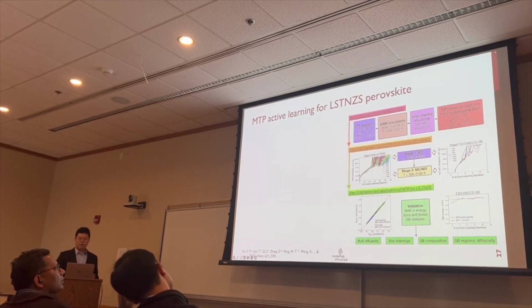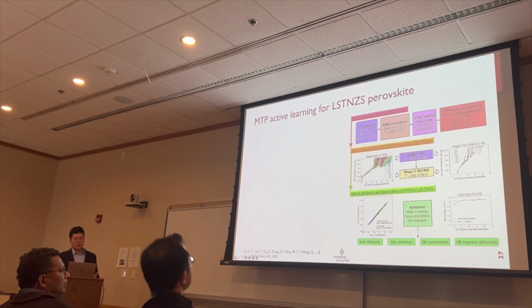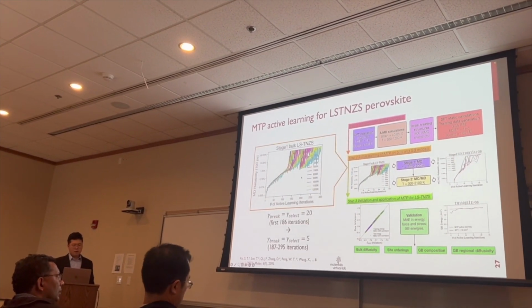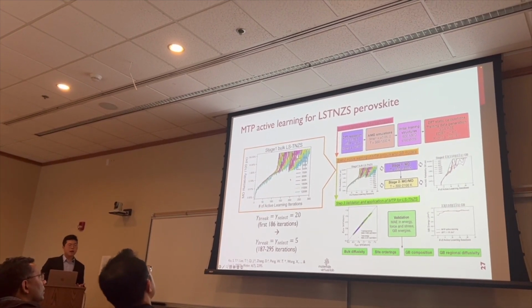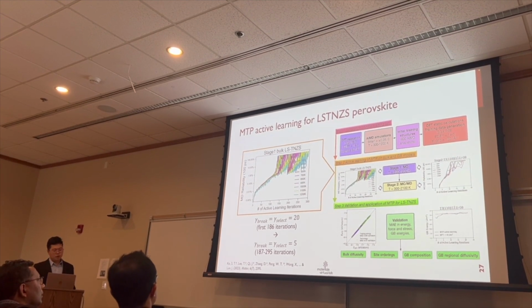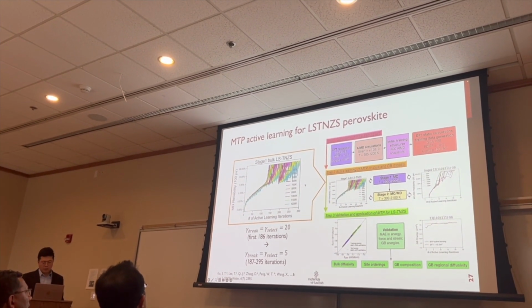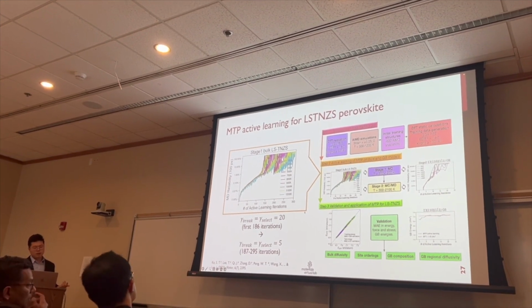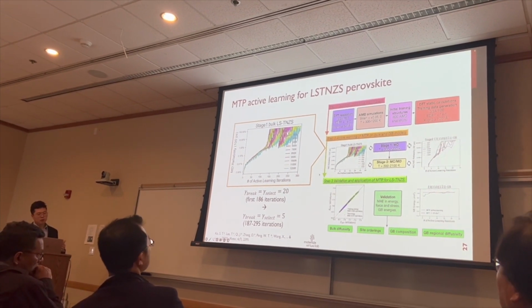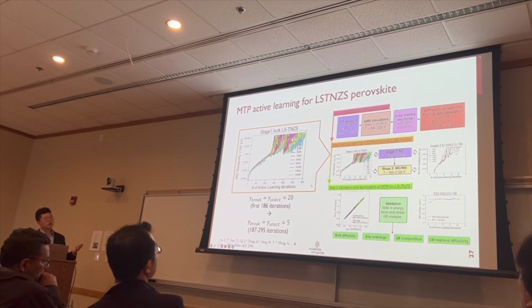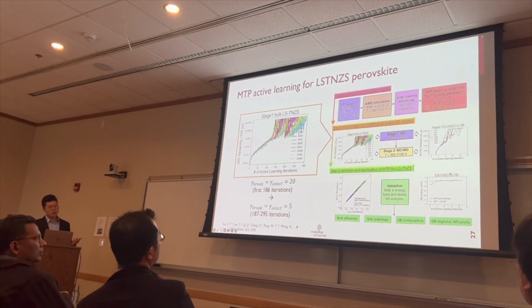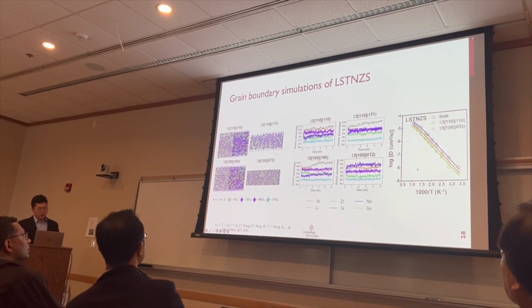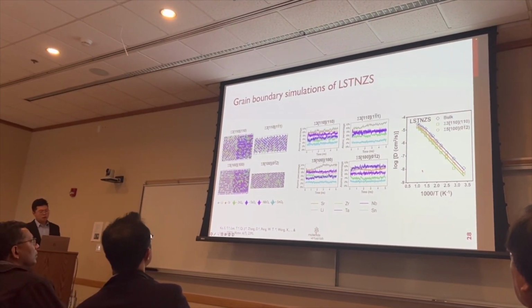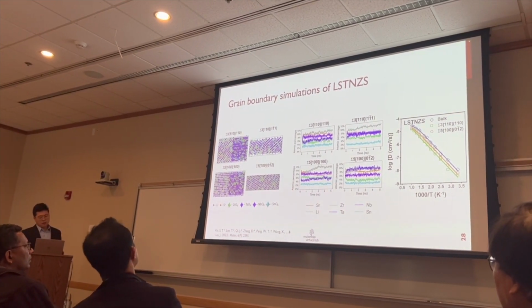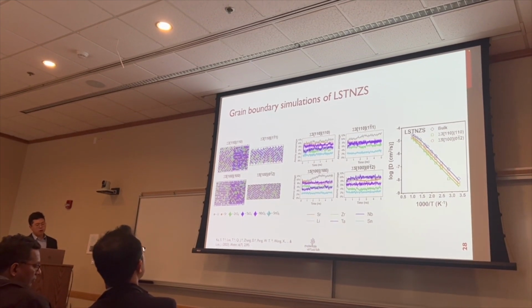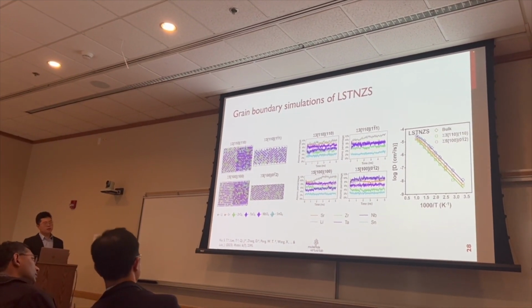And we applied the same workflow of active learning to construct MTP for this LSTNZS system. This time I want to highlight a little bit that we did spend a lot of effort to get this MTP converged, which took us more than 200 active learning iterations. But once the simulation is converged, it tells us that our MTP is reliable to simulate up to more than the experimental calcination temperature. And also we got very good matching with the DFT grain boundary energy. And similarly, we applied this moment tensor potential to study the grain boundary composition and diffusivity. In this system, we also got comparable results for the LSTNZS with the result in LSTZ 0.75.